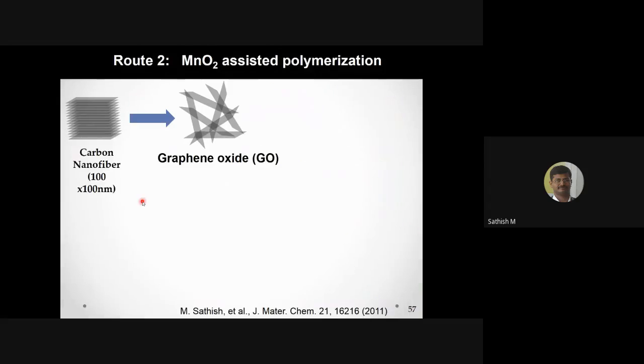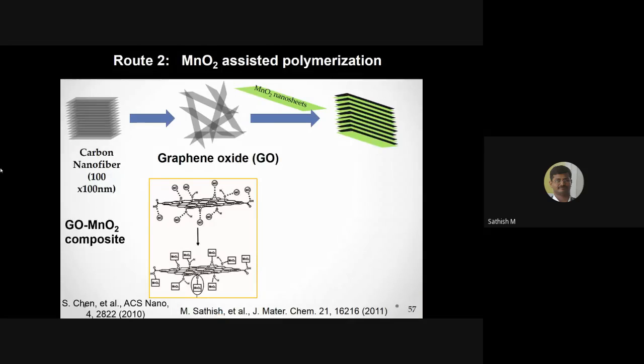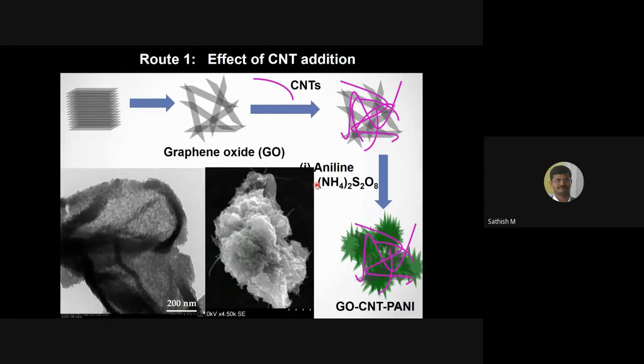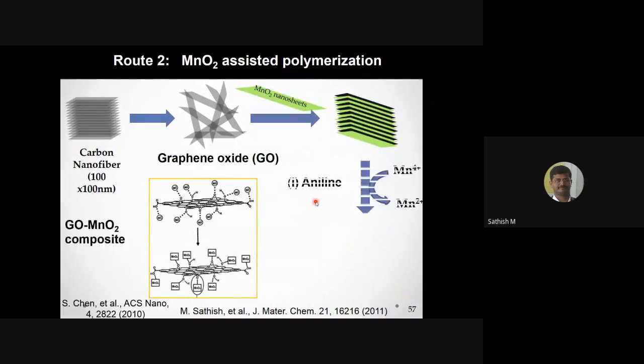On the other side, what we have done is we made a graphene sheet. We also made manganese oxide nanosheets. We made a graphene manganese oxide stacking, because the functional groups on the graphene surface have attraction with the manganese ions. So there is an interaction between the graphene and the manganese oxide sheet. When you have graphene oxide dispersion and add manganese oxide nanosheets, you get this kind of assembly because of electrostatic interaction. Then we add some aniline solution without any polymerizing agent. In the previous case, we used a polymerizing agent. Here, we will not add any polymerizing agent.